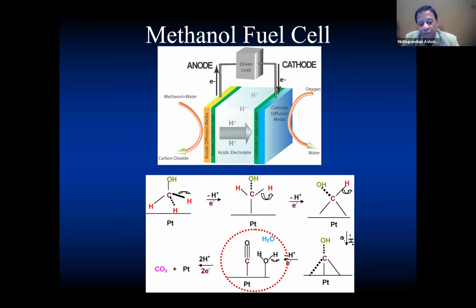Those who are working in electrochemistry found out that rather than having a single platinum nanoparticle, if you have a platinum ruthenium alloy nanoparticle, then ruthenium can convert the carbon monoxide into carbon dioxide. So there won't be any poisoning. So our aim here is to use sonochemistry to make platinum ruthenium alloy nanoparticles, which are less than 5 nanometers in size. Conventional processes cannot do this.